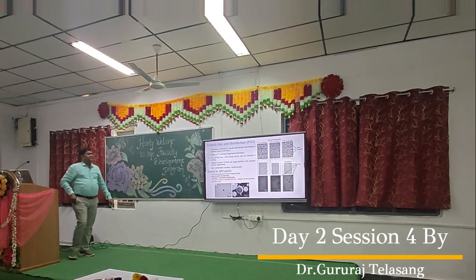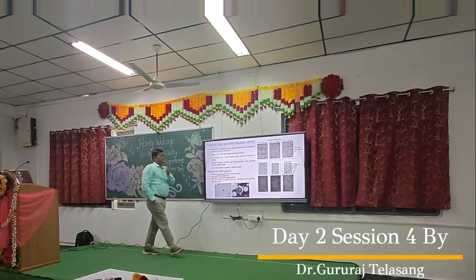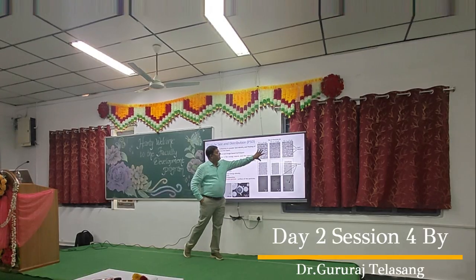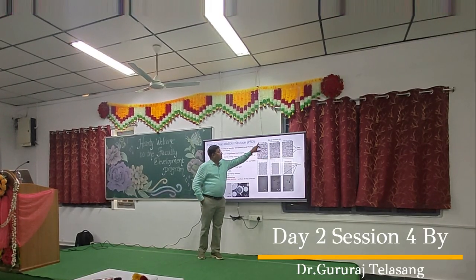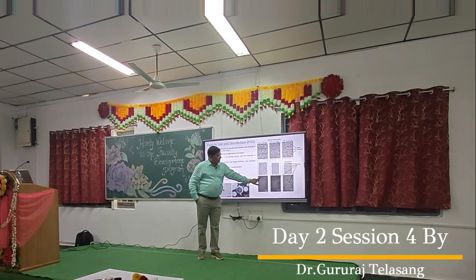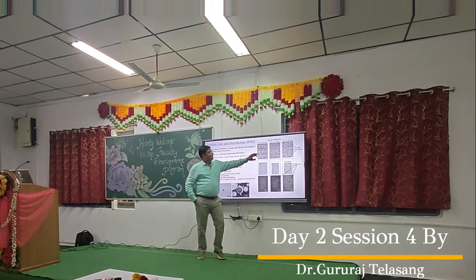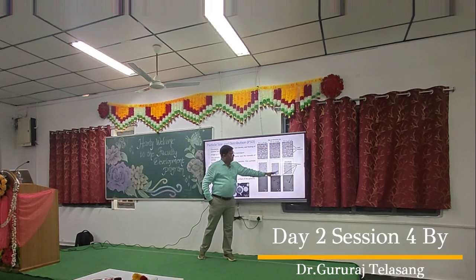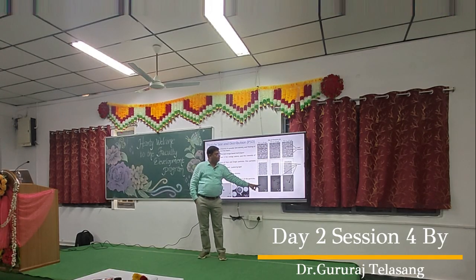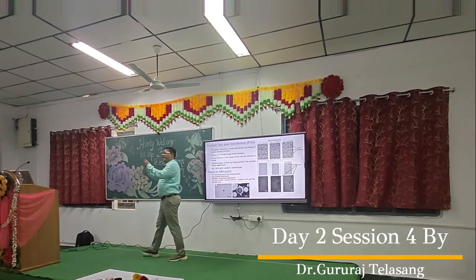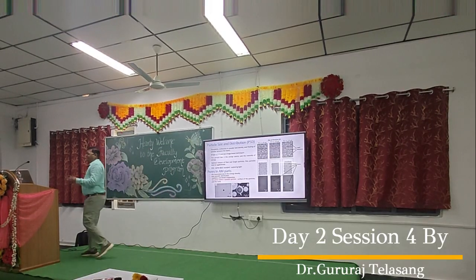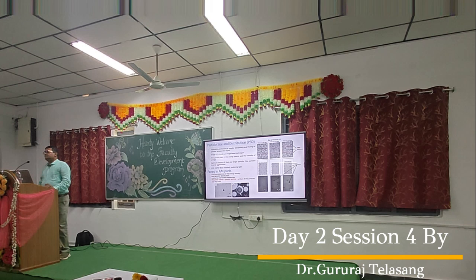This is the packing. How? That's what I was telling you. Different sizes will matter. The fraction range matters. So when you start with 16 to 63 micron, you will end up with no porosity because of the powder. Here 16 determines the finer fraction, and there is a coarser fraction. This is the particle size we look for, because of packing density. How nicely they get packed determines how well they will be melted, spread and fused together, and minimum porosity you can achieve.